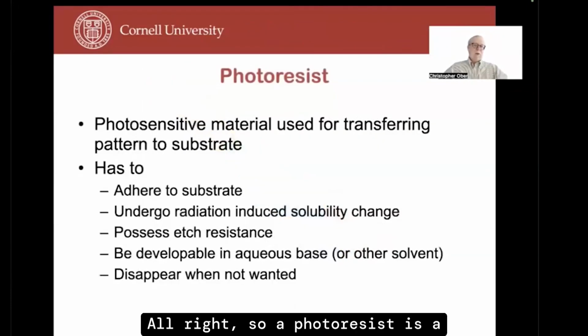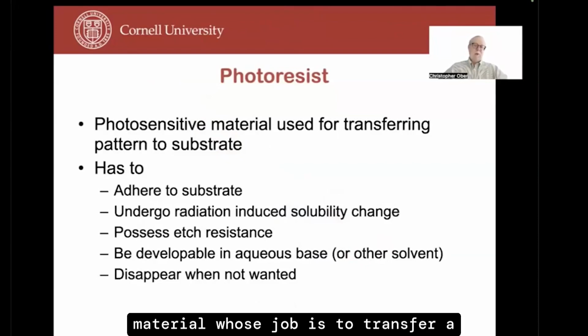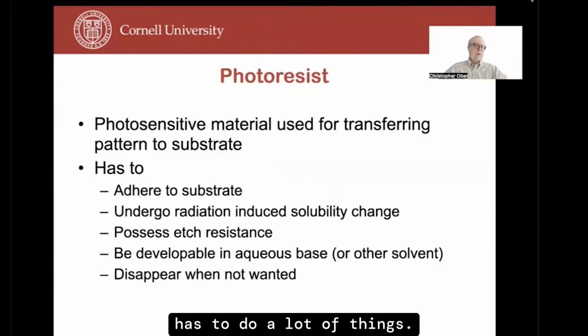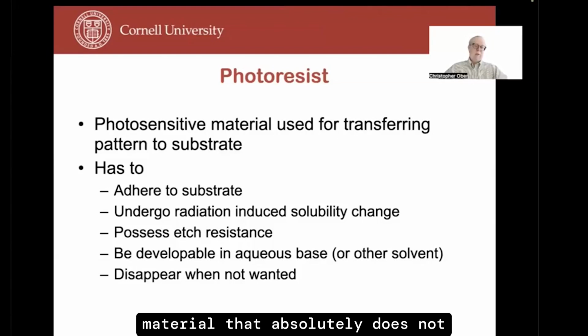All right, so a photoresist is a very critical photosensitive material whose job is to transfer a pattern into a substrate. But it has to do a lot of things. It has to stick to a substrate. It has to undergo a radiation-induced solubility change. It has to have etch resistance. A photoresist has to resist something, and it's through the etch resistance. It has to be developable, preferably in aqueous base. It can be in other solvents, but water as a developer is preferred. And basically, you want it just to vanish when it's not wanted. So it's an incredibly important material that absolutely does not appear in the final device. In the end, it all has to go away.